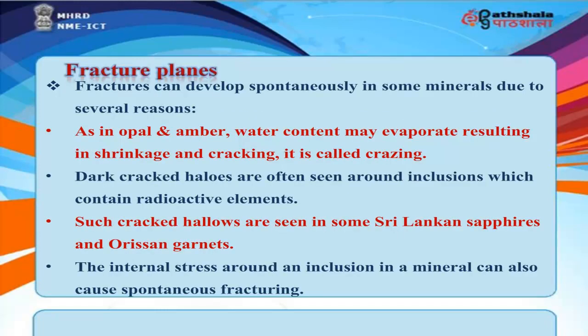Fractures can develop spontaneously in some minerals due to several reasons. As in opal and amber, water content may evaporate, resulting in shrinkage and cracking. It is called crazing. Dark cracked halos are often seen around inclusions which contain radioactive elements. Such cracked halos are seen in some Sri Lankan sapphires and Orissan garnets. The internal stress around an inclusion in a mineral can also cause spontaneous fracturing.